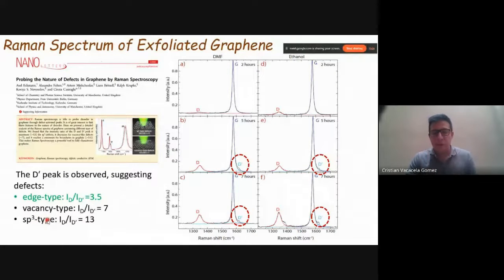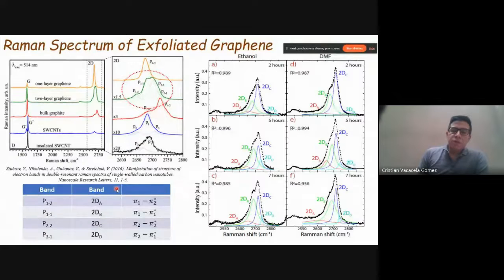I will try to illustrate when we talk about graphene oxide what the meaning of sp3 defects is. But please keep in mind, in our case, when we take this ratio, our numerical value for every sample, of course, up to say 7 hours of sonication, is close to 3.5. And of course, the type of defects we introduce in our exfoliated graphene is just the edge-type defects. This is another way how you can identify or interpret the Raman spectrum in the concept of these numerical values, and to write, for example, a paper or scientific communication characterizing your graphene samples. Now, let me focus on the 2D band for the exfoliated graphene.